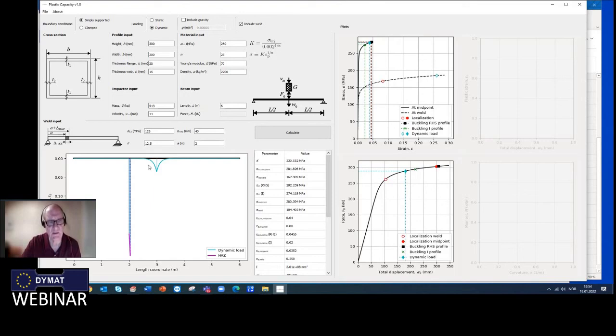So you will not have any problem with what happens in the center, but fracture will take place in the weld because you have a strong localization due to the fact that you have a small zone where you have reduced the material properties or yield stress. But you have increased the hardening, of course, but this tends then to localize all strains. And this is one of the challenges with aluminum, that when you weld, you have to be aware of where you put the weld compared to the deformation of your structure. So yeah, I think that this ends my talk.